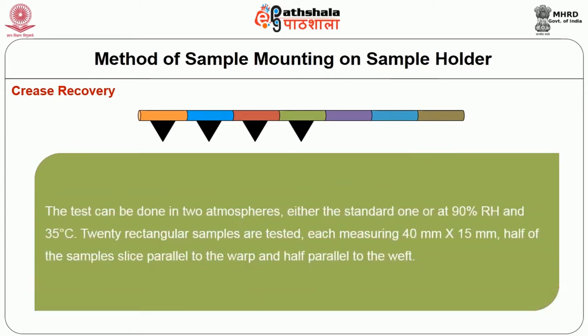The test can be done in two defined atmospheres, either the standard one, 65 plus or minus 2 percent RH and 20 degrees Celsius, or another one, 90% RH and 35 degrees Celsius. 20 rectangular samples are tested in this method, each measuring 40 mm by 15 mm. Half of the samples are cut parallel to the warp and half parallel to the weft.